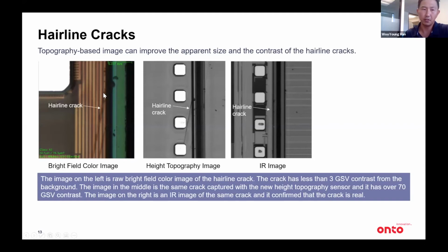On the left side, on the color image, this is showing a typical hairline crack from the die surface. As you can see, this is very thin and has a low contrast. In this case, this hairline crack has around 2 micron width. It's long, but very narrow. So something like this is very difficult to see with the traditional bright field and dark field imaging method. And on the far right, I have an infrared image. Even with the infrared image, these types of fine hairline cracks are very difficult to see. So we've been struggling to find these kinds of fine hairline cracks from the die surface, and we had to come up with a new way to image to find these types of cracks better, right?